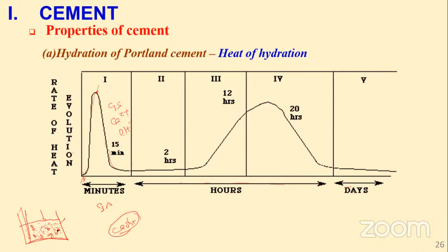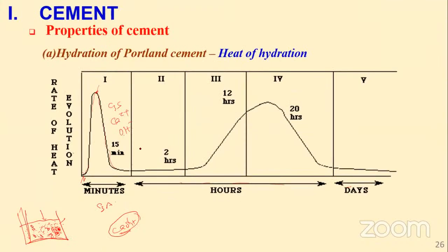Okay. So when crystals are forming, remember they are also inhibiting. The system is saturated. And the unreacted particles are now being surrounded by these crystals, calcium hydroxide. But when they crystallize, they become heavy. So you see now the reaction, because water needs to penetrate and reach these unhydrated particles. That's why the reaction slows down. Okay? That's why the reaction slows down. And this dormant stage, because we say phase two, this is dormant, it gives us time now to transport our concrete to where we want to place it.